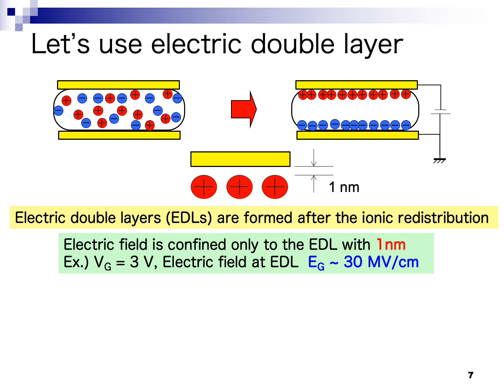What is the electric double layer? We sandwich an electrolyte with two electrodes and apply a voltage. The electric double layer is formed after ion redistribution. When we zoom in on the interface between the electrolyte and the electrode, the electric field is confined only to the electric double layer, with a thickness around 1 nanometer, depending on the size of the ions. So if we apply 3 volts to the electrolyte, the electric field at the electric double layer becomes as high as 30 megavolt per centimeter.